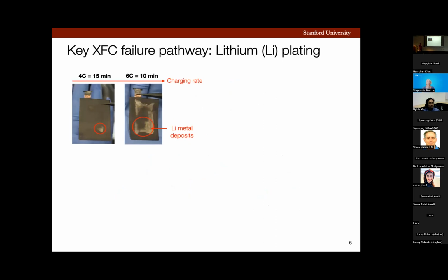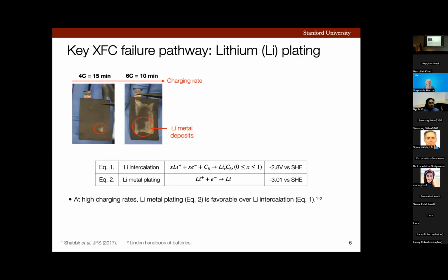Here, I'm showing two custom-made battery pouch cells that were charged between 10 and 15 minutes, and both of them experienced deposition of this whitish material on the surface of the battery anode. This white material is lithium metal, and this process is lithium metal plating, which is given by equation 2 here.